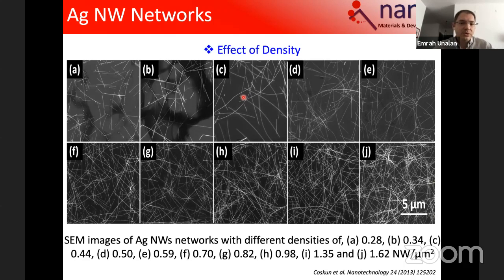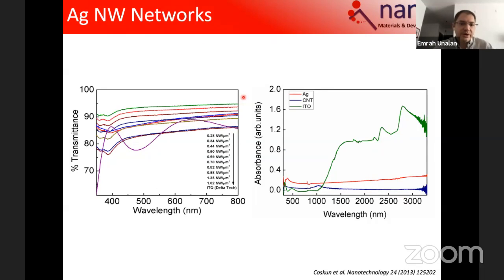And then we spray coat these things onto the substrates. We can control the density of nanowires. Density of nanowires allows us to control the transmittance and at the same time the conductivity, or if you wish, the sheet resistance of these materials. And I should also show this. These materials are infrared transparent, as you see over here, whereas the conventional typical ceramic ITO is not.